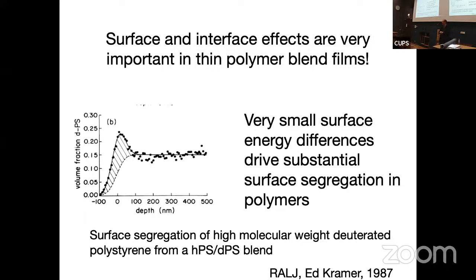But it's not a hugely important effect, because the length scale of that segregation is very small. But this curious feature of polymers is that because the polymer molecules are very long, their entropy of mixing is very small, as I mentioned. So even tiny differences in surface energy can create a big difference. And this is illustrated in a piece of work from long ago. Even the difference between a hydrogenated polymer and a deuterated polymer is enough to drive this surface segregation.